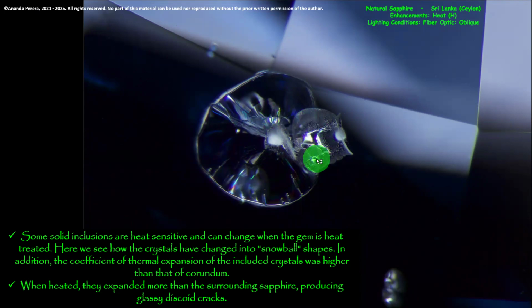In addition, the coefficient of thermal expansion of the included crystals was higher than that of corundum. When heated, they expanded more than the surrounding sapphire, producing glassy discoid cracks. This is a big glassy discoid, and these are the glassy discoids. See, so it gives the main evidence regarding the heat treatment. We are moving to next.